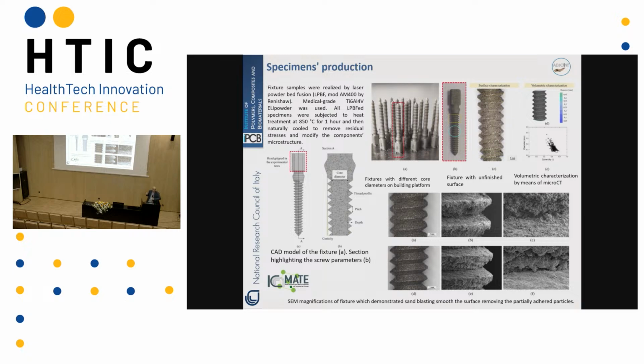And what is important is the surface of this object. It is necessary to have the right dimension of roughness on the surface in order to allow the growth of the cells on the surface. Also, here you see, for example, all the particles that are not attached on the surface must be removed. It was very difficult, this step. Also, we had to ask a company outside of the project for cleaning this by sonication, because they have the right equipment and the certification that ensure that no free particles are present on this object. Imagine, the dimension of this particle is very difficult to manage or to use.